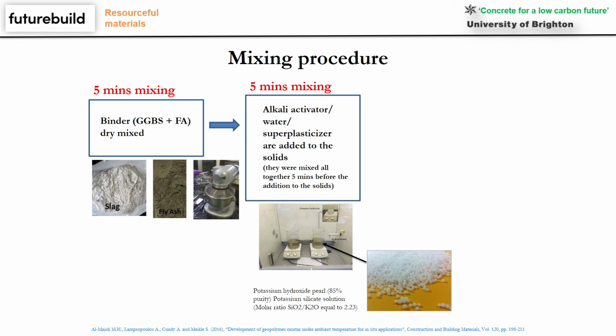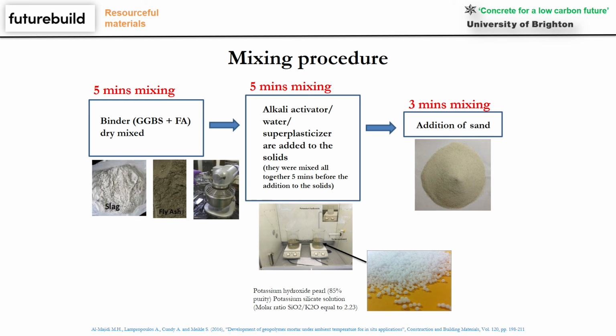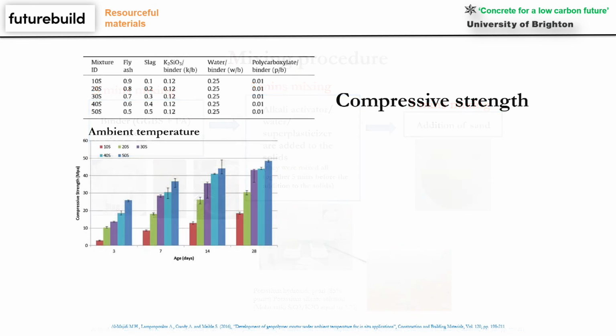The chemicals, potassium mostly, were used here, some superplasticizer and sand. And actually, the concept was to optimize the process, so to find what is the optimum mix design in order to have good early strength and also good ultimate strength without any heat curing.